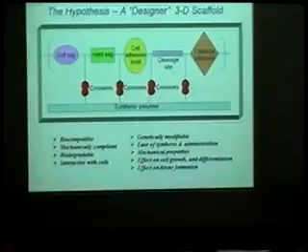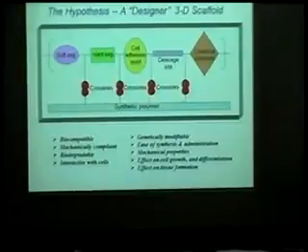And of course, if you want to interact with cells, you can put different kinds of cell adhesion modules into the chain. And you also want the scaffold to be able to be remodeled, so putting in enzymatic degradation sites is going to be important. It should also be possible to incorporate growth factors, for example, a tethered growth factor as part of the scaffold, rather than adding a soluble growth factor, which is going to be easily diffused out and consumed. And if necessary, a synthetic polymer can be incorporated just to maintain the mechanical strength and add water solubility and swellability of the scaffold through these very well-defined crosslinks.